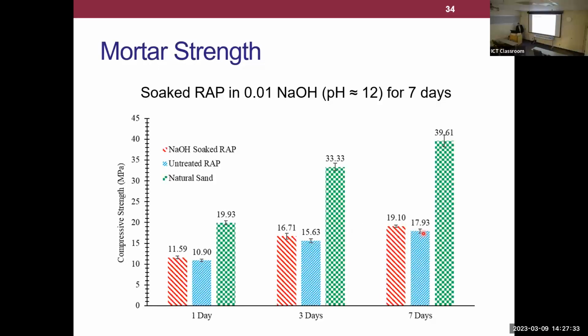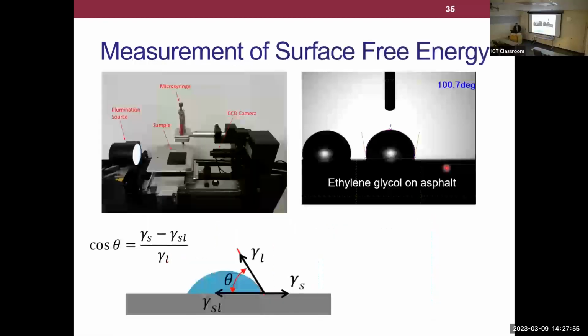So these means are statistically different, 95% confidence. These other ones are not. So we're seeing a very marginal increase in strength. Of course, we're not meeting the equivalent of our virgin aggregate, but we're seeing a slight increase. So was it really worth the effort? Probably not. So next thing we tried to figure out, why isn't this NaOH working?